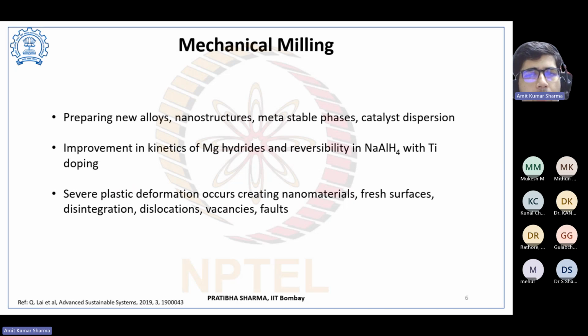Now come to mechanical milling. In mechanical milling, we can prepare new alloys, nanostructures, metastable phases, and catalyst dispersion. So it can improve the kinetics of hydrogen reversibility. It can improve the kinetics in Mg hydrides, and reversibility in NaAlH4 with Ti doping, and severe plastic deformation occurs, creating nanomaterials, fresh surfaces, disintegration, dislocations, vacancies, and faults.